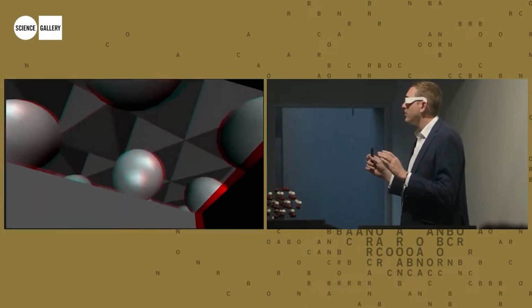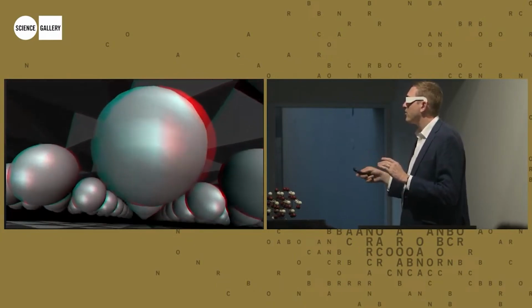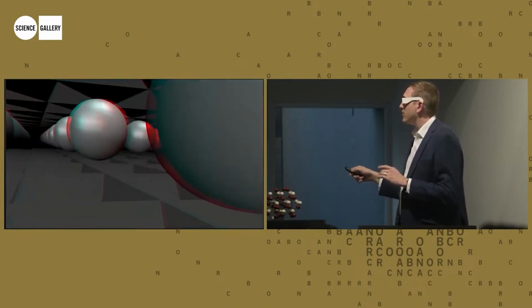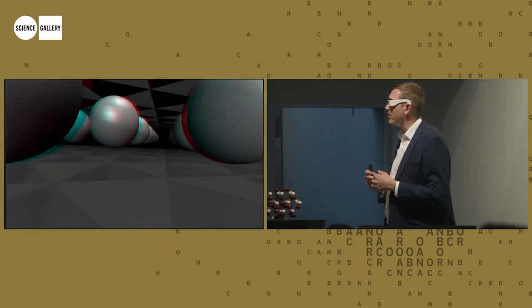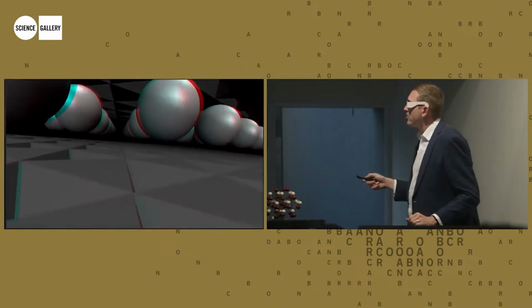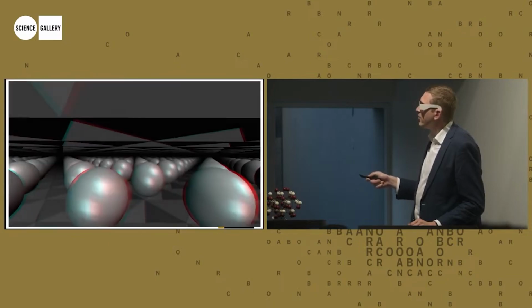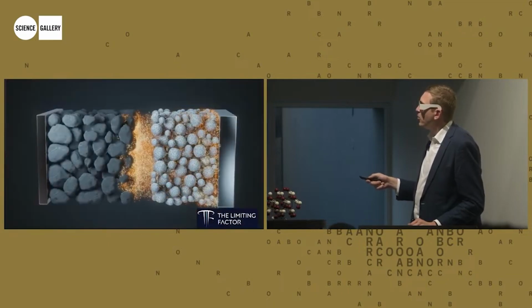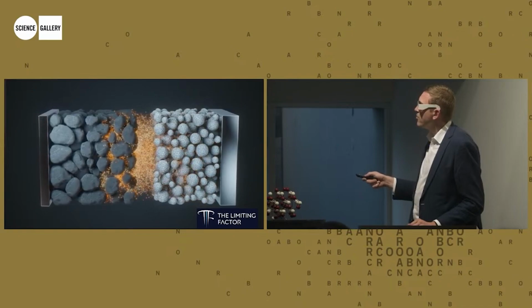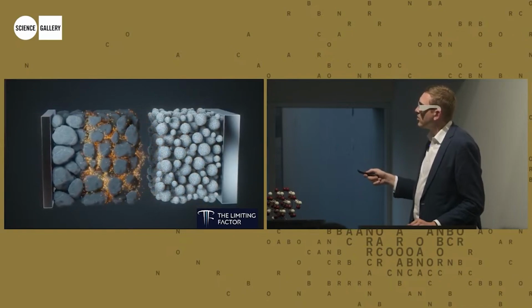It's a little hard when you don't have the VR headset to know how to drive around, but you can see here that you've got layers of metal oxide and layers of... all right, sorry about that. Not very good driving. So when you charge your battery, the lithium goes from in between those metal oxide layers to the other side of the battery. What's important here is the lithium needs to go through the liquid, but the electrons cannot.